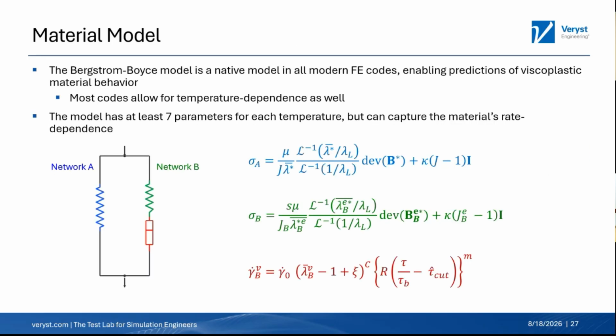So I talked a little bit about the test data that we have. So what I did in the next step here, and if you remember back to a slide at the beginning, we talked about that process where we do testing, then material modeling, then finite element simulation. This is the material model we calibrated to this test data. This is called the Bergstrom-Boyce model. One reason I like it is that it's an advanced model that captures elastomer-like response very well. I call it a nonlinear viscoplastic model. Some people call it a nonlinear viscoelastic model. We could have debates about that all day. I'd be happy to do that with you over a coffee or a beer.